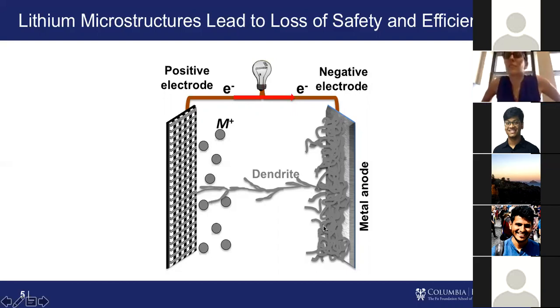So what that means is that's a lot of surface area for decomposition reactions from the electrolyte to start taking place on the surface of this lithium metal. And obviously these dendritic-like structures have high surface area as well. So if the cell is starting to heat up, you have more decomposition that's occurring, and you have lots of surface area for it to occur on. So it's basically just the perfect scenario for thermal runaway to start to occur once you have this dendritic or microstructural lithium start to grow in your cell. So this is really what we're sort of interested in studying in my lab.